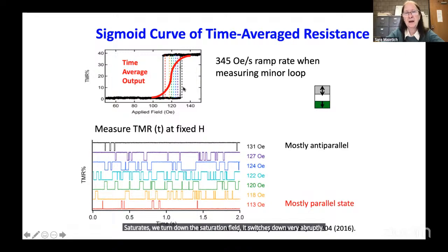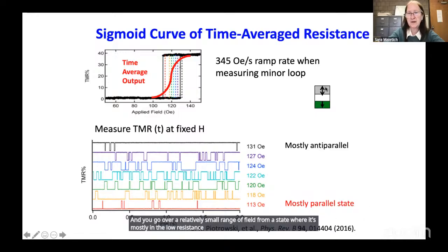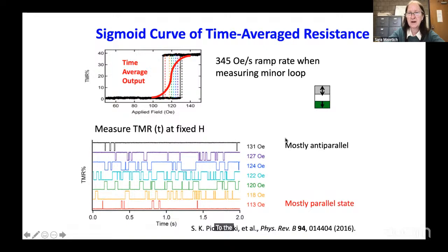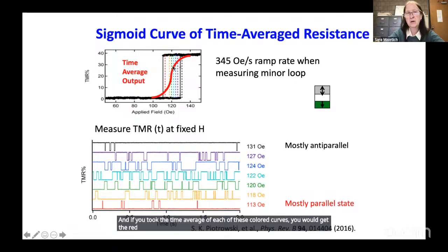But if you sit at one particular field in this open area and measure as a function of time, you see that it's not a fixed value. It has thermal fluctuations between two levels. These are offset. And you go over a relatively small range of field from a state where it's mostly in the low resistance or parallel magnetization state to the high resistance most of the time, mostly in the anti-parallel state. And if you took the time average of each of these colored curves, you would get the red S-shaped curve. That's the sigmoid curve that's very important for any probabilistic computing application.